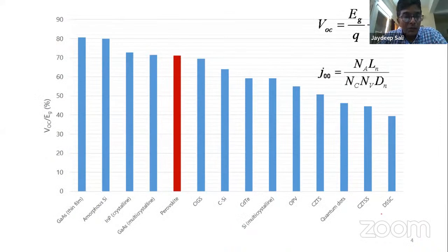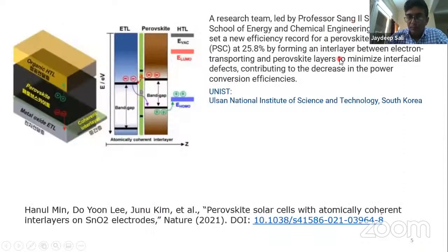There is another advantage of using perovskite as compared to the other candidates for thin films. So this is a chart wherein you can see the ratio of open circuit voltage and the band gap for different materials. On the x-axis, you can see different materials, and the y-axis shows the ratio of open circuit voltage and the band gap. So here there is a relation which relates the open circuit voltage with the band gap.